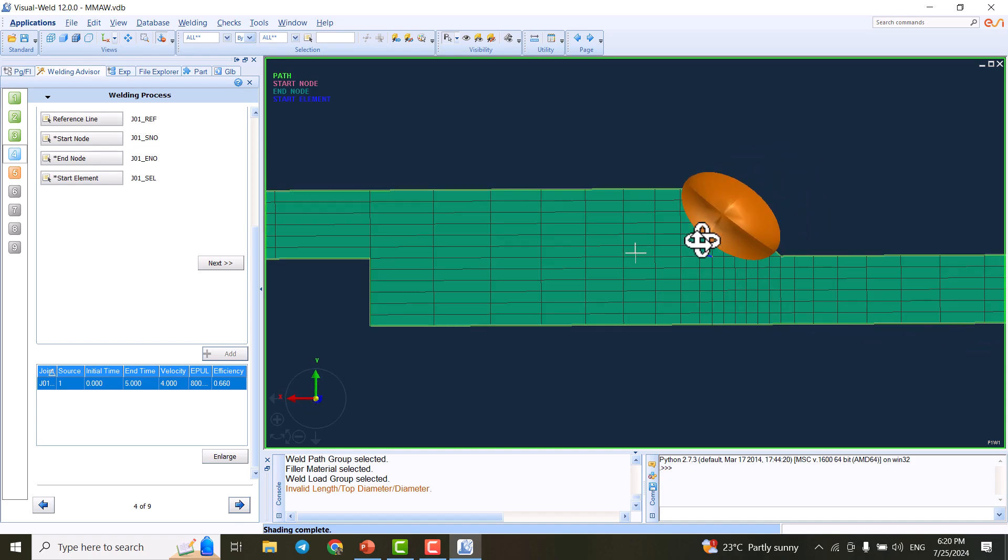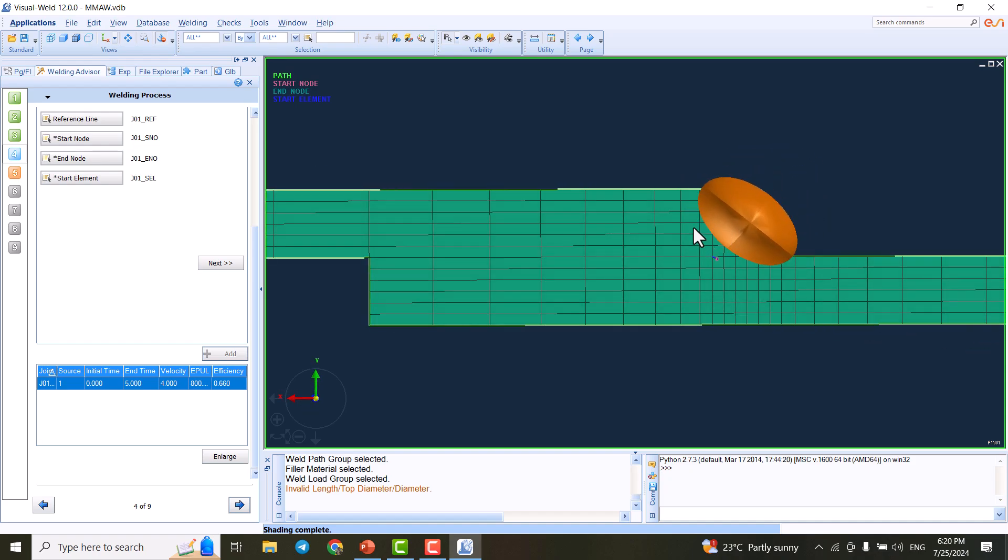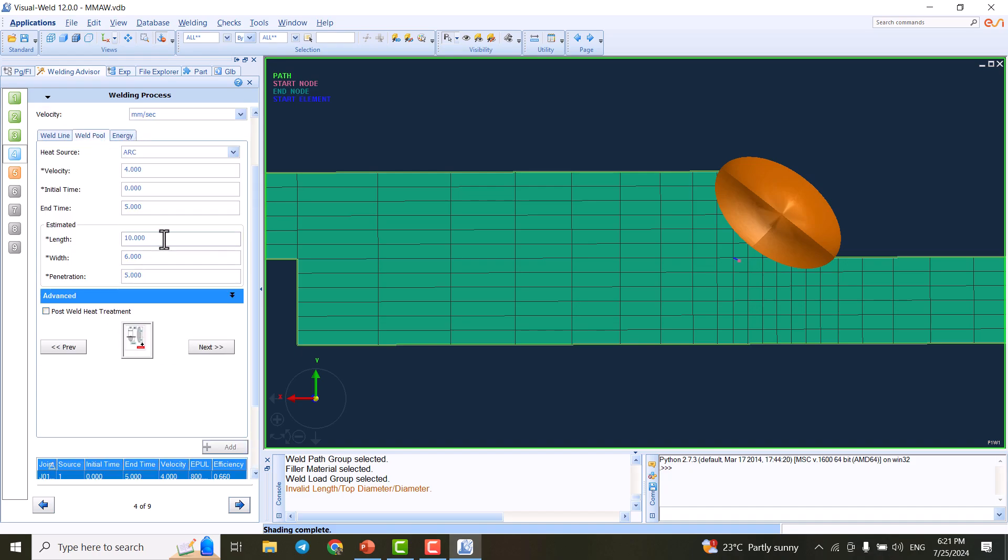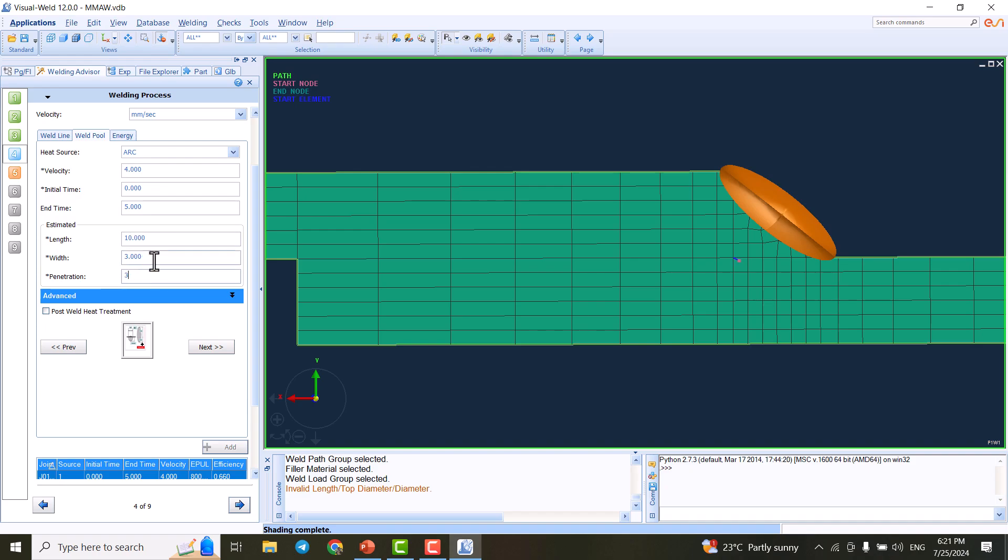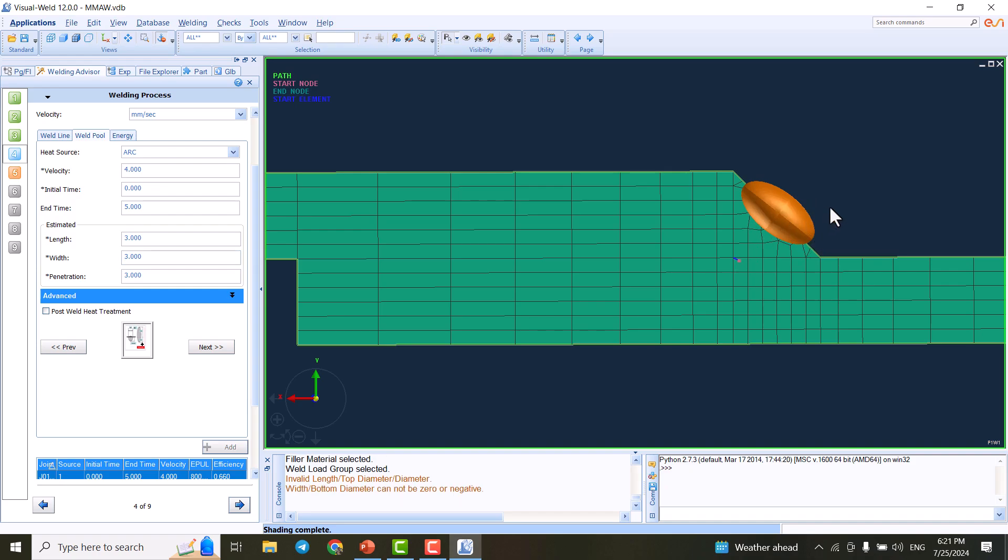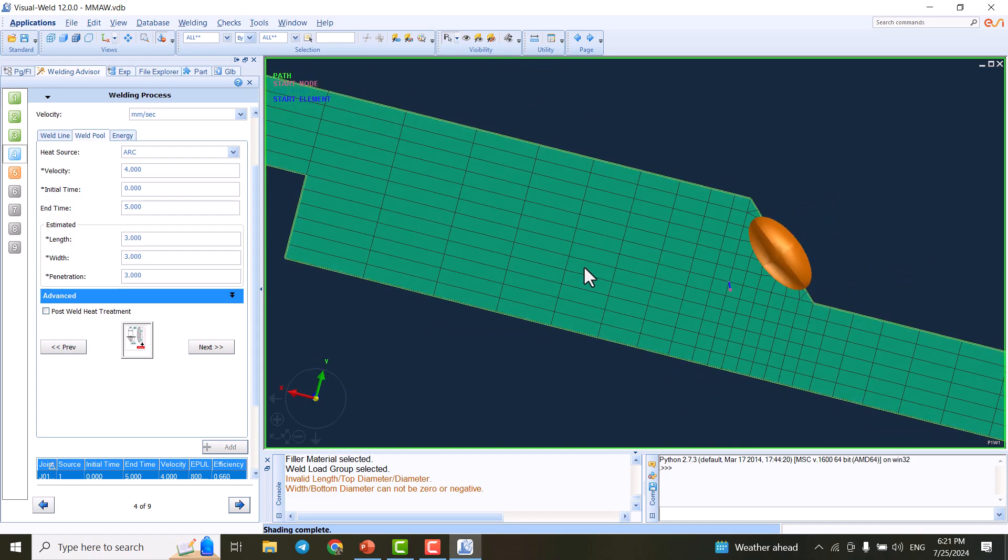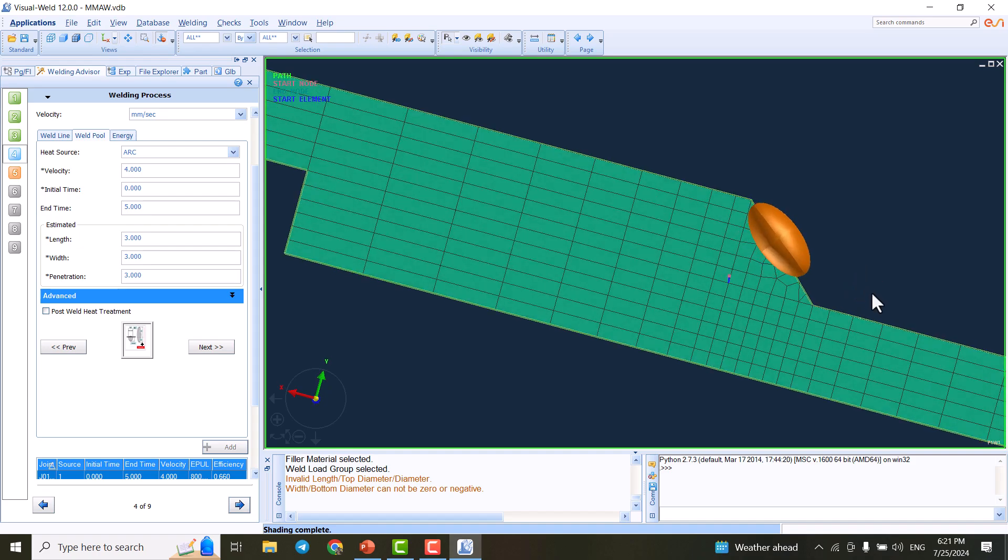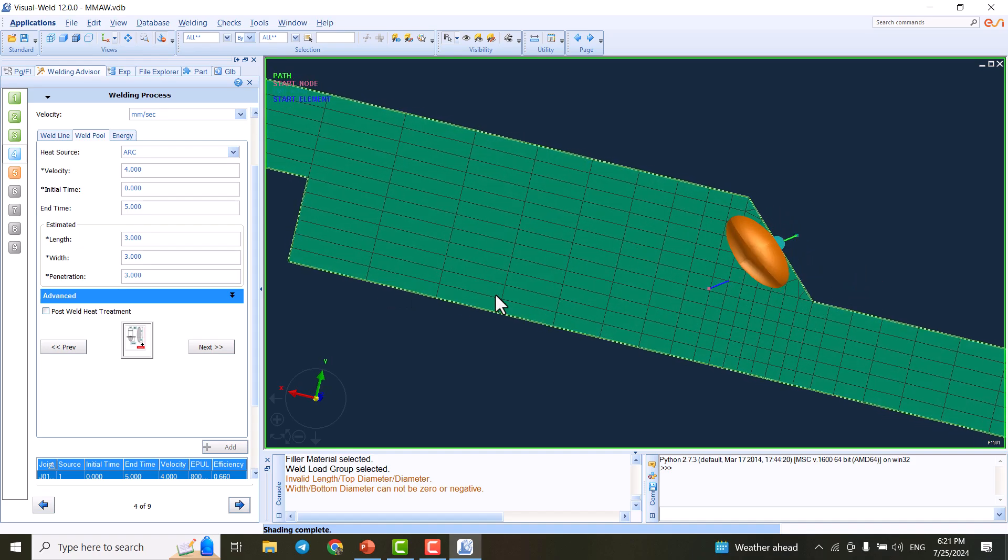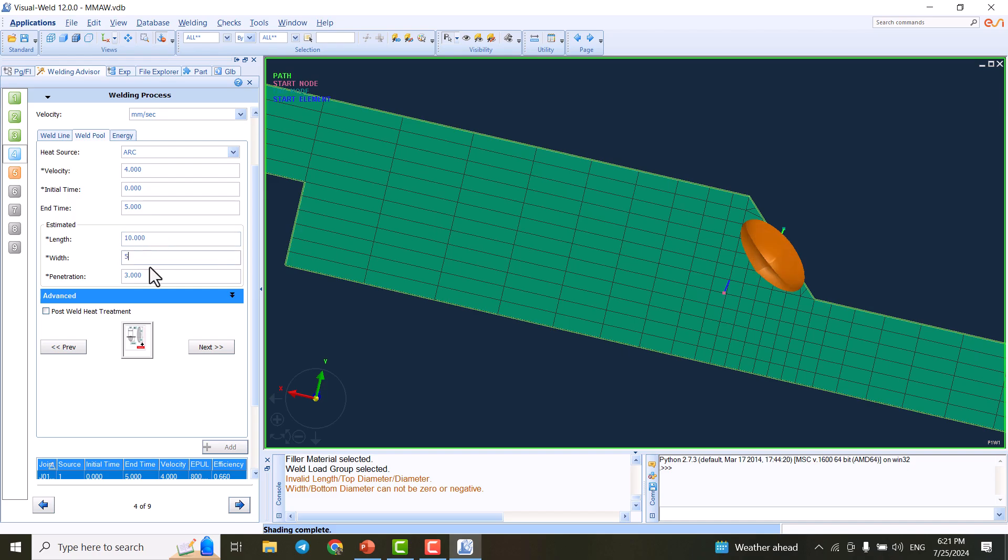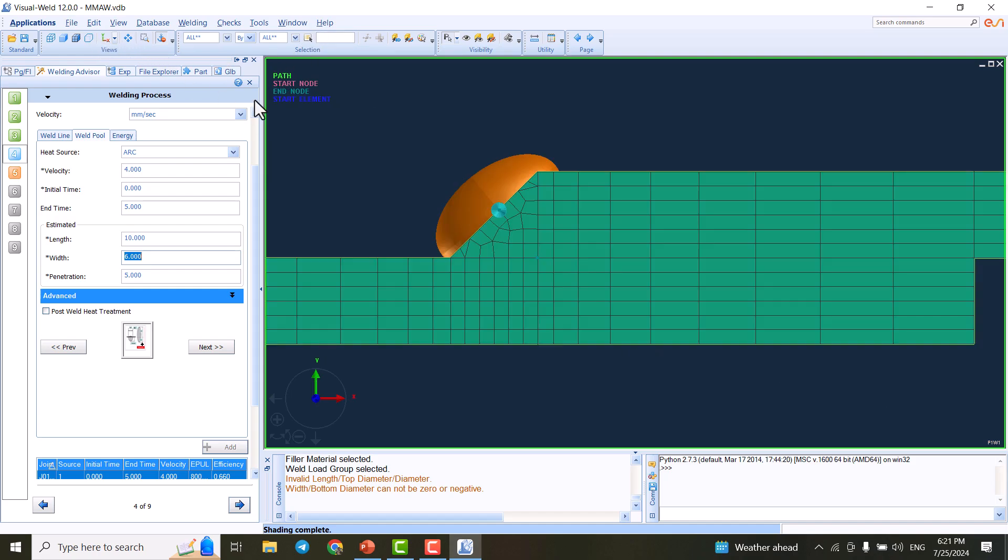Let's say we're going to have a narrower width, like 3. We see that the root of the weld is not covered by the weld, so it's not enough. If we change all to 3, we have a narrower ellipsoid which is not good. We have to select parameters in a way to cover the root of the weld. These numbers are okay. If we did the analysis and it wasn't good, we can do it again.